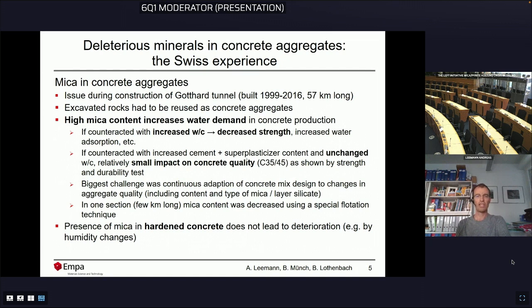A high mica content increases water demand to reach a certain workability in concrete production. If you counteract this with adding more water, which means increasing water-cement ratio, this results in a decreased concrete strength, increased water absorption, and so on, which just means decreased quality. If it is counteracted by increasing cement and superplasticizer content and unchanged water-cement ratio, relatively small impact is observed, and this is shown by a lot of strength and durability tests.